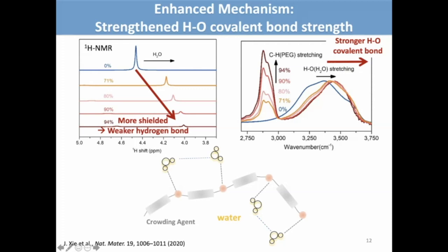At the same time, FTIR shows that as we increase PEG content, the OH stretching has a blue shift through this FTIR spectra. And we can see that means that the OH stretching becomes higher in energy with stronger bonding. So this evidence supports our hypothesis that with crowding agents, we're able to strengthen the OH bond in the water molecules, and therefore discourage the water splitting reaction.